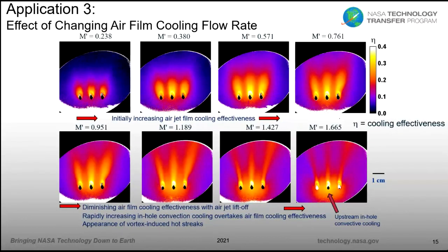Now, it turns out you can look at the effect of the cooling more clearly if, instead of looking at the temperature maps, you determine a parameter called eta, the cooling effectiveness. What that does is it takes the absolute values of the temperatures out of it, so you can more fairly compare across different temperature regimes. What this shows, I believe more clearly, is that as you increase the cooling air flow, the cooling effectiveness becomes brighter, meaning that the magnitude of the cooling effectiveness is getting greater, as well as its spatial extent. But then again, you come to a point where as you continue to increase the cooling flow, you get less and less well-defined cooling effectiveness, and you can hardly see it at the highest airflow because the jet is lifted too far off the surface.